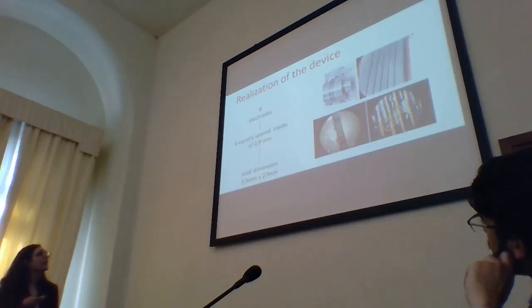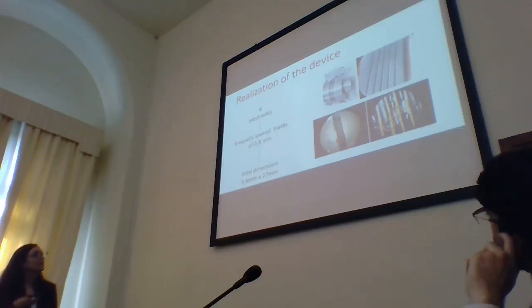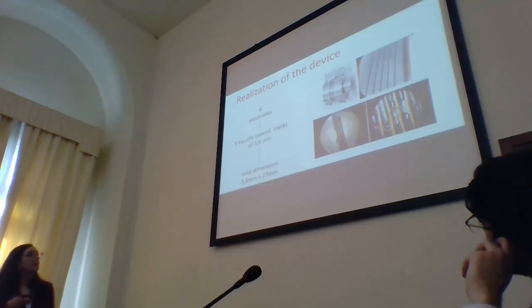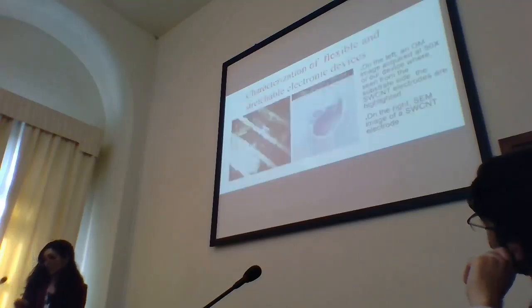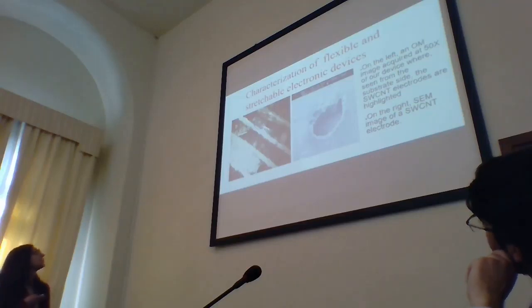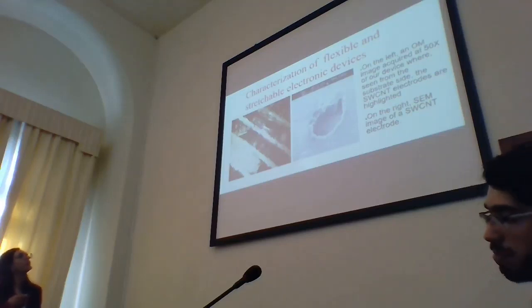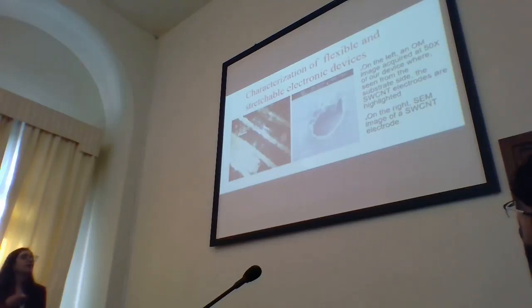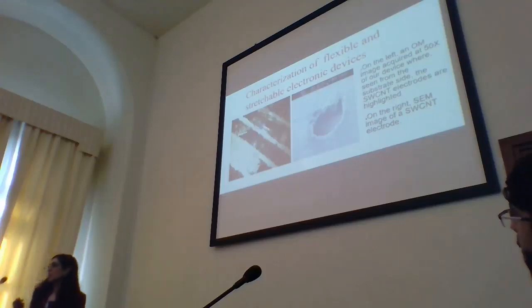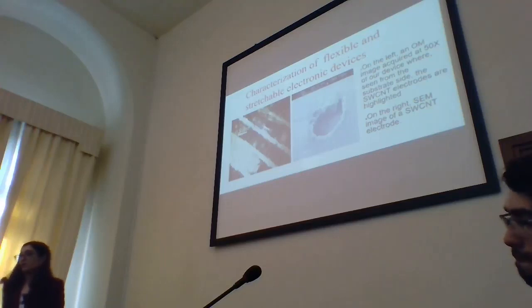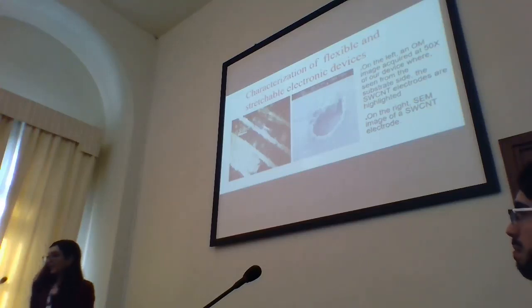This is our device without a connection. This is from the carbon nanotube side, and this is an optical image of the device, but from the polyethylene side. And in particular, these are our electrodes. In this slide, I show the same image and also an SEM characterization of the electrodes. We can see that nanotubes are compact and uniform, and from this image, we can see that this diameter is about 15 microns. We can go down with the diameters to work with the upper frequencies, and we have done this for another device.